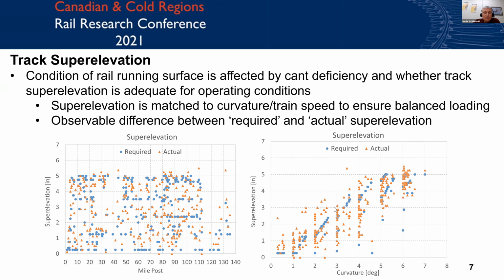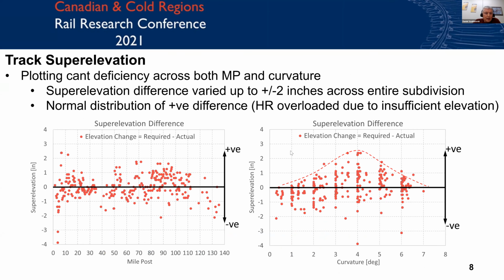So we decided to take a deeper dive into that, and we plotted again the milepost for those super elevation differences between the required and the actual. So taking the required minus the actual, and then seeing what has the cant excess and what has the cant deficiency, meaning more high rail damage and more low rail damage. And for the milepost, again, you see that the difference sort of looks like a point cloud. But if you organize that by the curvature, the picture becomes much more clear.